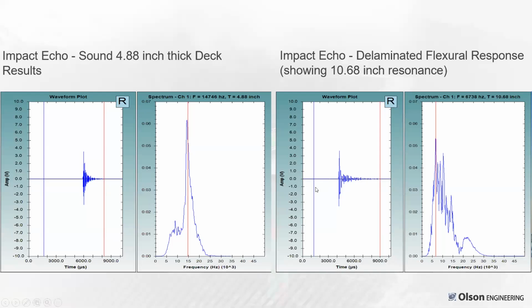And we were able to then use that data to determine slab conditions. On the left here, we have the time domain followed by the spectral response of a sound location. This is a nominal 5-inch thick concrete deck. This is showing an echo at 4.88 inches, which is pretty dang close to the 5-inch thickness that's expected.